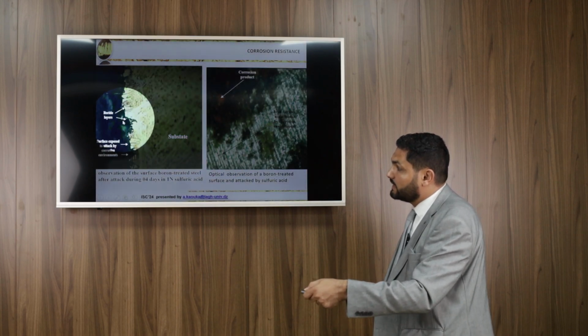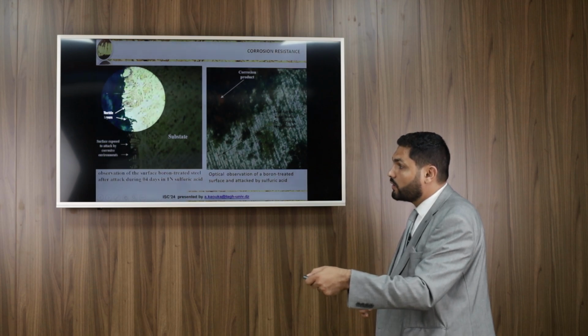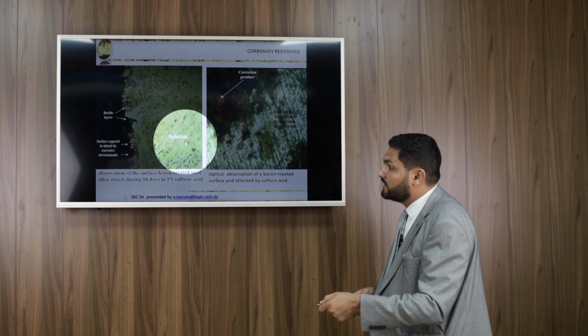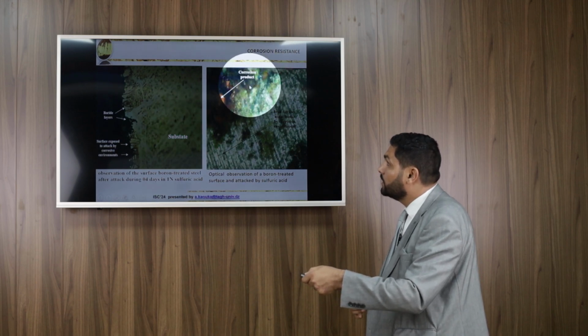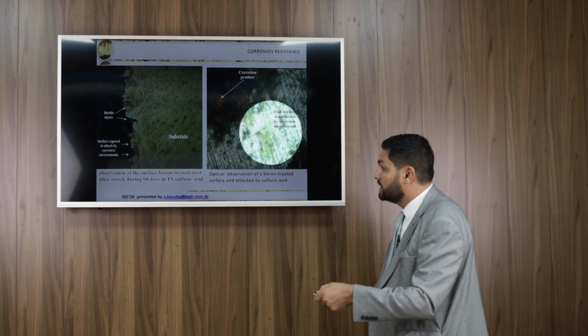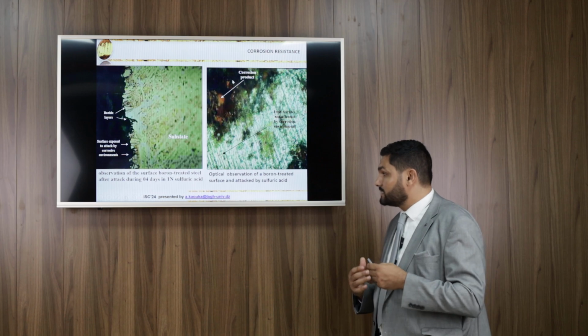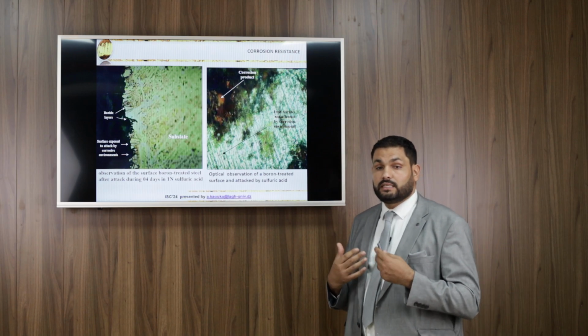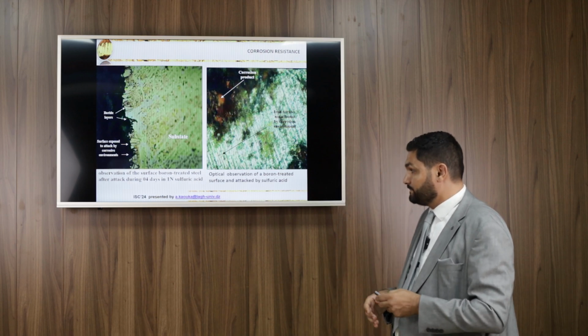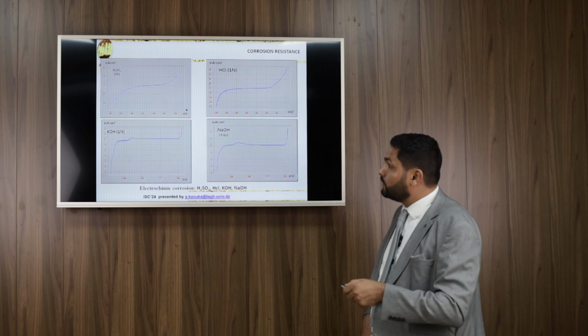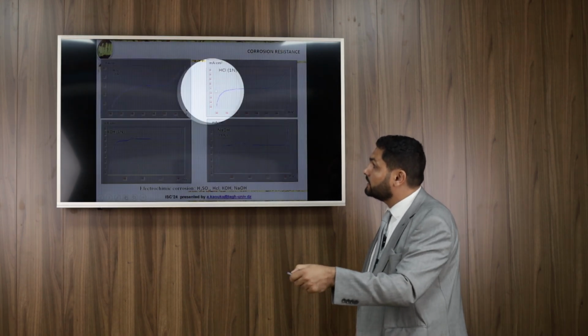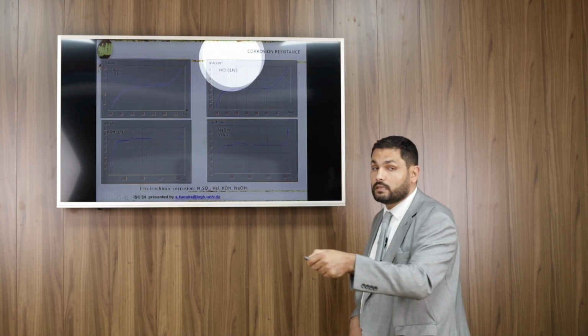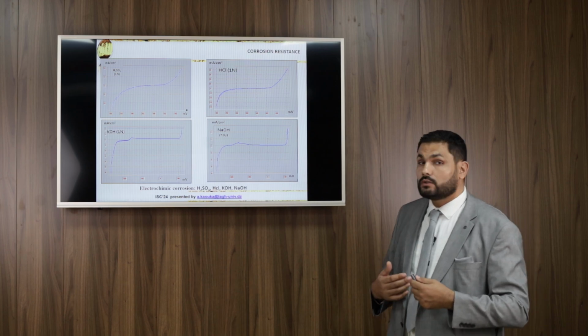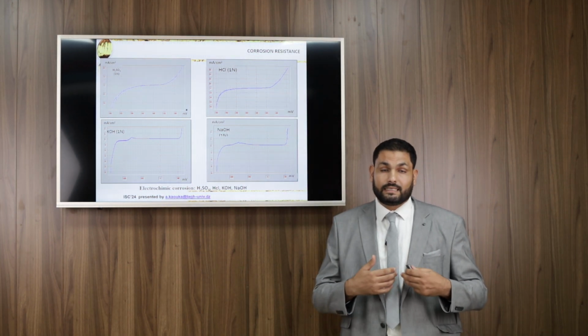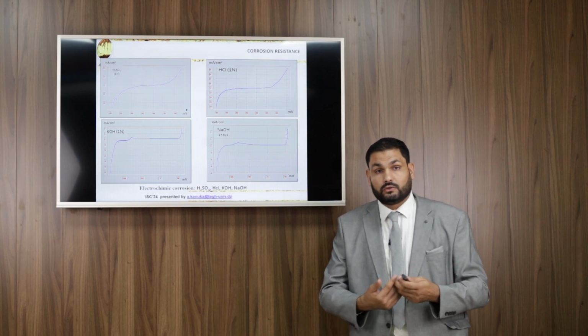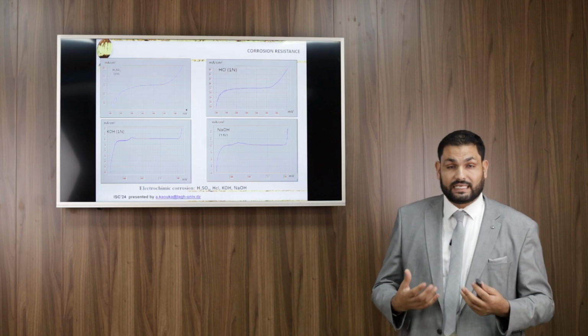This is the boride layer, this is the surface exposed to attack by the corrosive environment, and this is our substrate that we protected. This is corrosion produced without treatment, and this is with treatment. This is the optical observation of the boron treated surface attacked, in this case, by sulfuric acid after 94 days. We used sulfuric acid, hydrochloric acid, and also sodium hydroxide and potassium hydroxide as alkaline solutions.